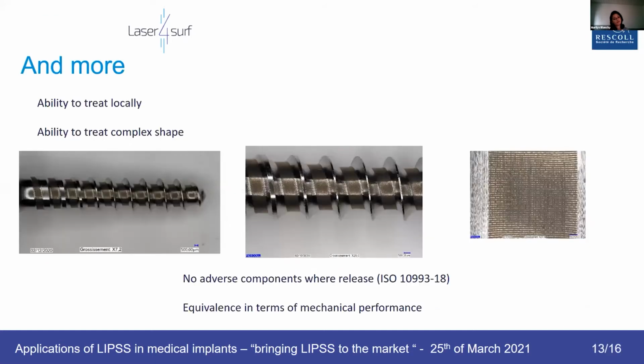And finally, a few words. A very interesting finding we had in the project is that, as we said this morning, we can treat very locally, but we can also treat very complex shapes. Here, this is a spinal screw. We can treat only a very specific area with a nice laser pulse macro topography. This is not a very good magnification, but we clearly have LIPSS on each of the threads, which is very good for implants.